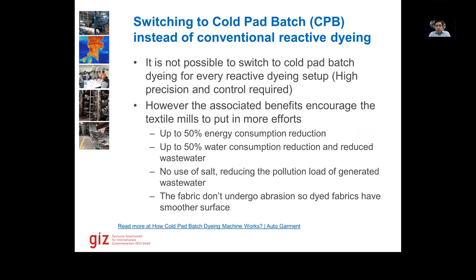Then switching to cold pad batch. This is a new, emerging technology. It reduces energy and water consumption by 50%. It does not require salt, hence reducing the pollution load. And there's no abrasion required on the fabric, so the dyed fabric has smoother surfaces as well. But obviously not every process can be switched to cold pad batch dyeing. Not every reactive dyeing setup can be converted. So there are some limitations. Obviously, one has to look at those limitations as well.